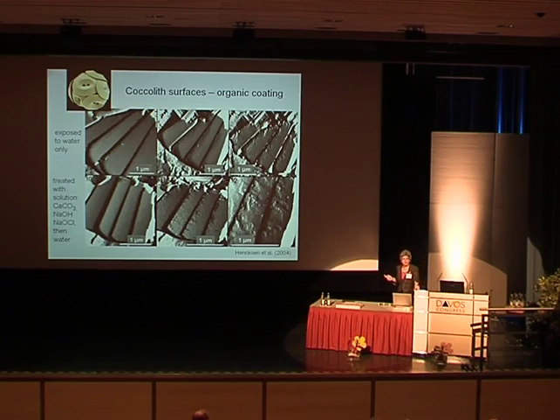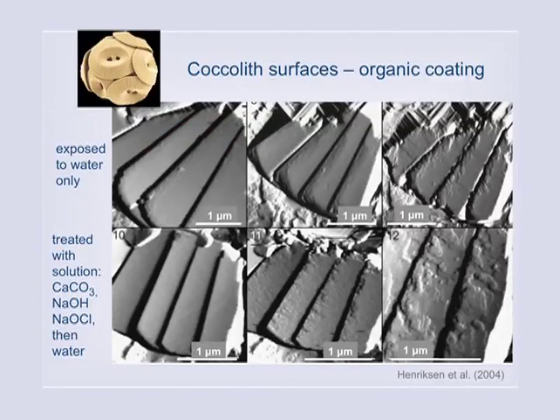calcium carbonate does. And that's quite interesting, because that has repercussions on how we're going to get that oil out of the spent reservoirs. So here we see some coccolith elements that have been exposed only to water. Now, you can see there at the edges, it's beginning to dissolve, but there's nothing in the middle. The middle is intact. There's no dissolution in the middle of the coccolith elements. Now, why? If you leave it longer, it keeps dissolving from the edges, and eventually it works in towards the middle. But there's still a large part that isn't dissolved.